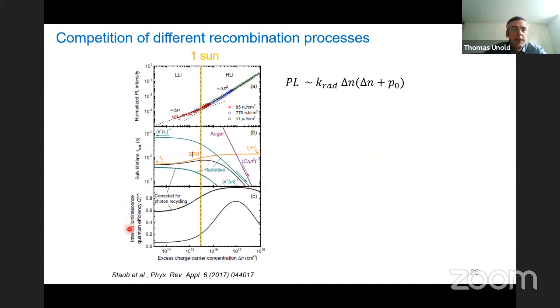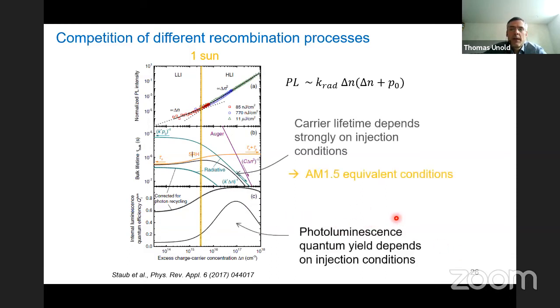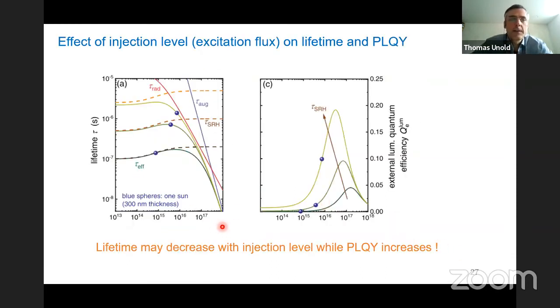And in the lower plot here is shown the luminescence quantum efficiency. You can see, let's look at this curve, that at very low injection it stays constant, then it increases and then it decreases again. This is due then to Auger recombination. And this is what I just said. And this has consequences. So this is shown here now for three different lifetimes. So let's see, this is 100 nanoseconds. This is about a microsecond. This is even larger. Again, here there are different contributions from different recombination processes.